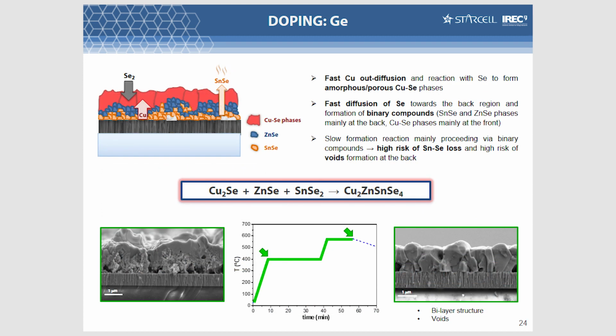Then, combining X-ray diffraction with Raman spectroscopy, I will not show it here because it's quite complex work, what we conclude is that in that case, the kesterite is formed via the reaction of the binary compounds. Copper selenium, zinc selenium, tin selenium binary compounds react to form the kesterite. And then when we finish all our crystallization process, we obtain quite good layers, but that can be improved.